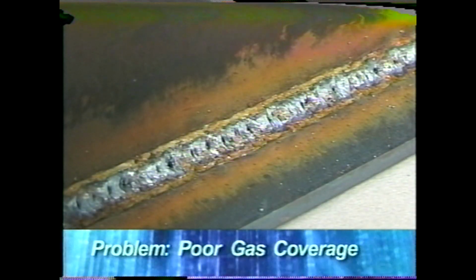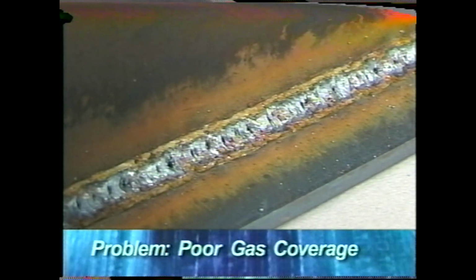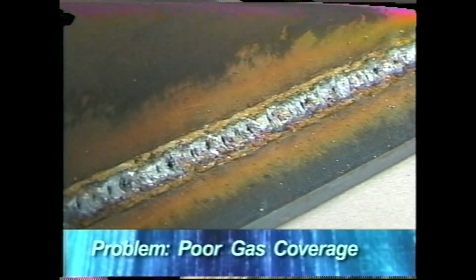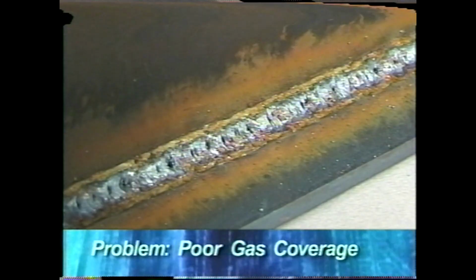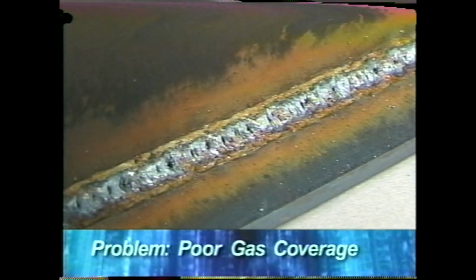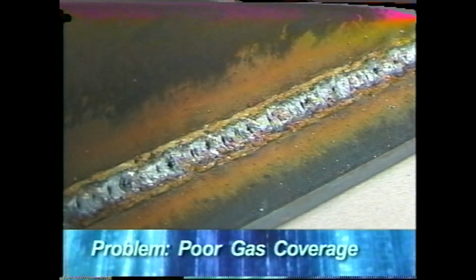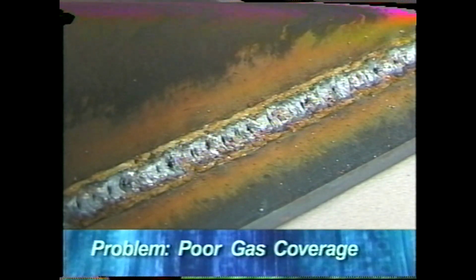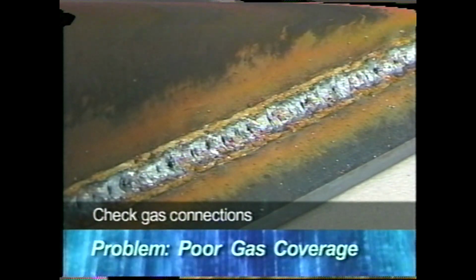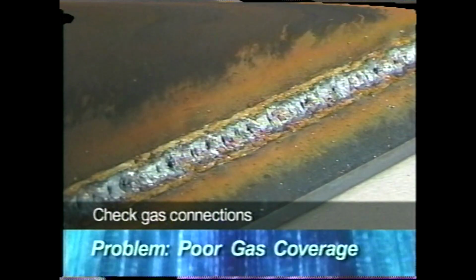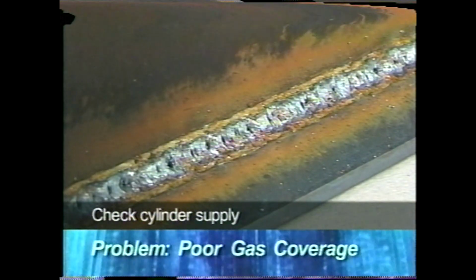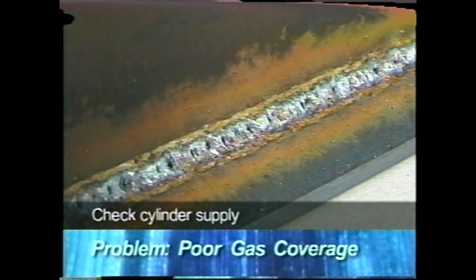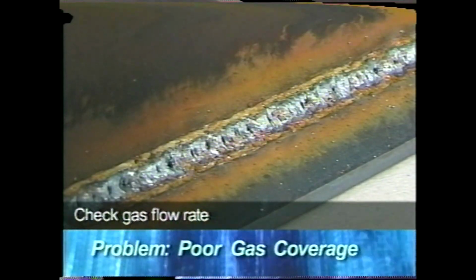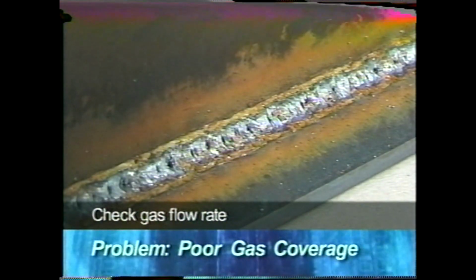Shielding gas protects the molten weld pool from contaminants in the air. Poor gas coverage or an incorrect flow rate can cause deficiencies in the finished weld, such as porosity, which is pinholes in the weld. Make sure all your gas connections are correct and secure. Check the flow gauge to be sure that the cylinder has sufficient gas, and check the gas flow rate.